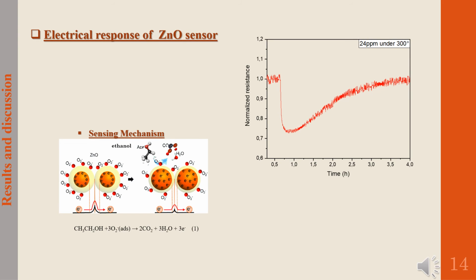In this slide, we have the electrical response of the zinc oxide sensor. We have the response under activated gas at a temperature of 300 Celsius. There is a decrease in the resistance of the sensor under ethanol, as shown in the right figure. The left figure describes the sensing mechanism. Under air, the adsorbed oxygen is bound to the surface and gives an initial potential barrier. When ethanol gas is injected, it reacts with the adsorbed oxygen species and causes the liberation of carbon dioxide, water, and electrons. The release of electrons leads to a decrease in the resistance of the sensor.